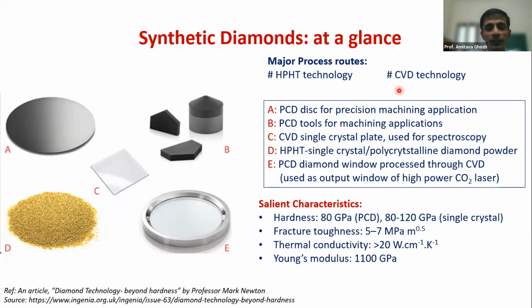So the same understanding was actually realized in the lab, not today, but almost in the 1950s. That day, it was a revolutionary exploration, and I would say a discovery. In the lab, this element 6 is converted to diamond under high pressure and temperature, following the same natural route. The pressure is as high as almost 40 to 50,000 times the atmospheric pressure, and the temperature in the capsule within which the graphite is converted to diamond is about 1500 degrees centigrade.